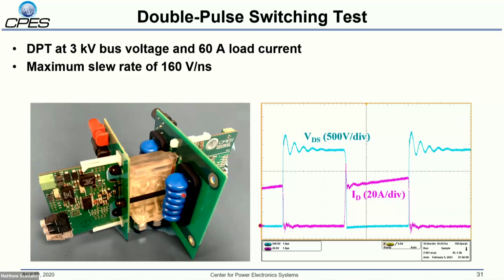So this is what the completed module looks like between its 2 PCB bus bars, and it's got a gate driver board mounted on either side for the high side and low side switch positions. And during my testing, I got this up to a bus voltage of 3 kV with a 60 amp load current and a maximum slew rate of about 160 volts per nanosecond, which is awfully snappy. I don't think you'd ever want to run this that fast, but I was curious how fast we could go, and that's how fast it got. That's with about a 300 milliohm external gate resistor.